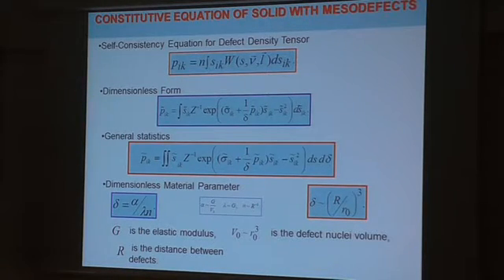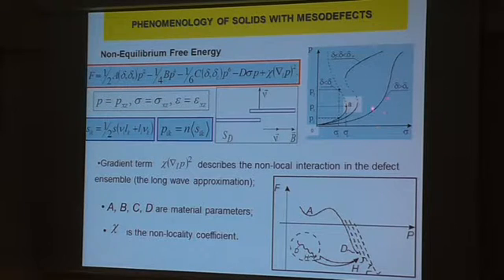When this equation was solved, it was found that there are two characteristic critical points in terms of this delta parameter, where we have very pronounced bifurcations, and these bifurcations are related to different mechanisms of structure-induced relaxation. For instance, this metastability area corresponds to the evolution of the dislocation substructure that I mentioned after the oral papers. But if we pass some characteristic scale, we have a new bifurcation with an infinite jump, and the corresponding nonlinearity was reflected in the form of out-of-equilibrium free energy release in terms of these parameters.